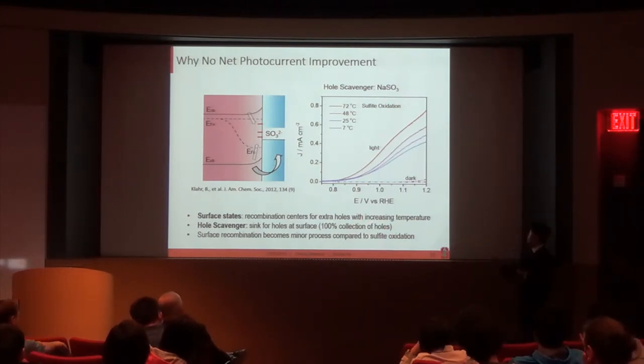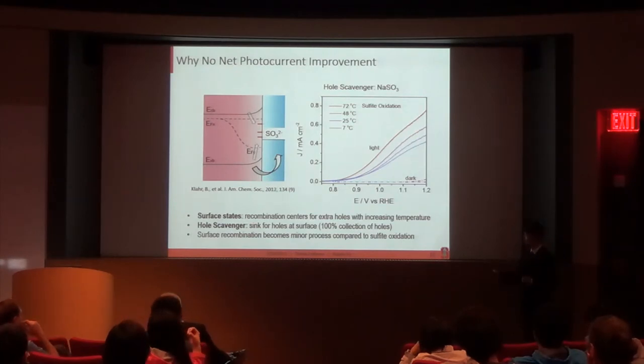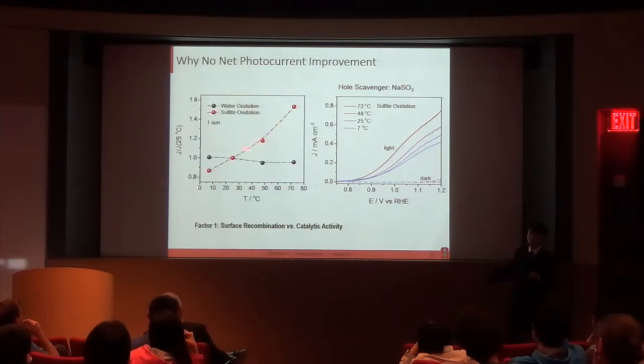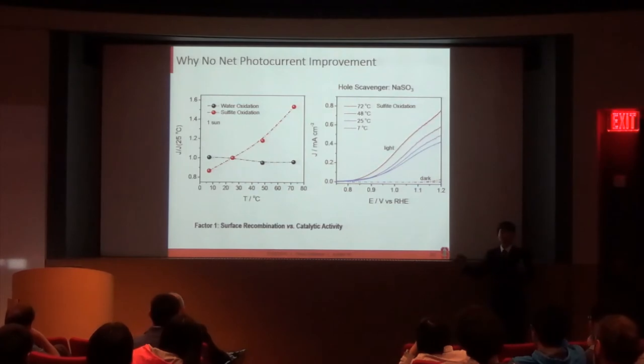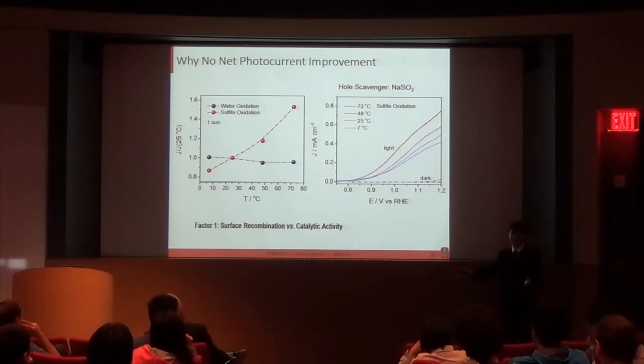So indeed, as we increase the temperature, we do see an increase in photocurrent. And such an increase is more significant if we compare the sulfite oxidation to water oxidation. So that confirmed our first hypothesis, that the competition between the surface recombination and the catalytic activity plays an important role in determining whether we will see a net photocurrent enhancement.